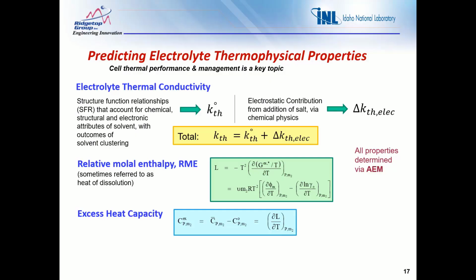So the net or total expression for thermal conductivity is the addition of those 2 terms. As we go down, there's a relative molal enthalpy, sometimes referred to as heat of dissolution, that's calculated. And this is derived directly from the thermodynamic term osmotic coefficient, the phi of m, so it's that over dT. And then we also have the presence of the activity coefficient, gamma plus minus. Through that, we're able to see the change in enthalpy as we add salt to the solvent system. From that, we can easily derive the excess heat capacity for the system. If we add that to the native heat capacity of the pure solvents, then we have the total heat capacity for the system.